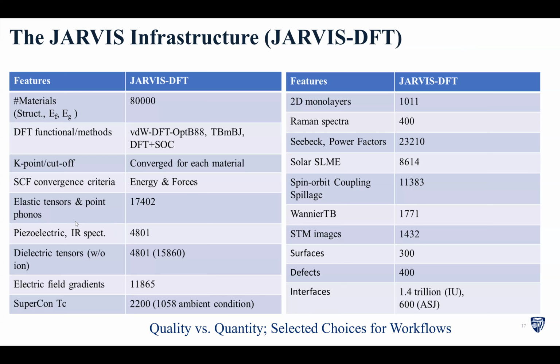We have data for elastic tensors, piezoelectric tensors, dielectric tensors, electric field gradient, superconducting transition temperatures, 2D materials, Raman spectra, Seebeck coefficient, solar cell efficiency, spin orbit coupling, spillage for topological materials, WannierTB dataset, STM images, surface, defect, and interface properties for up to 1.4 trillion interfaces, which is crazy, I mean, in my opinion.